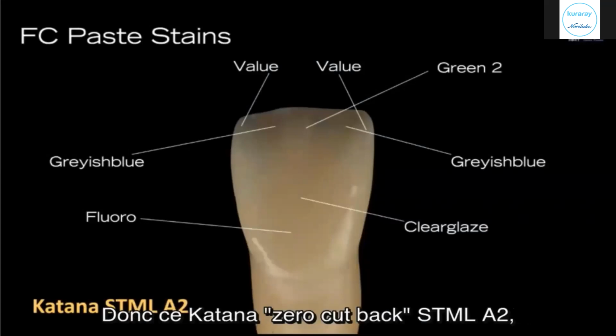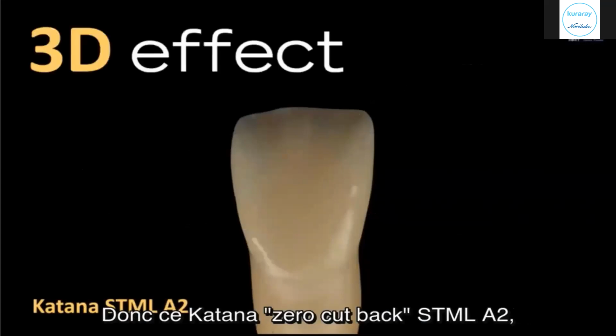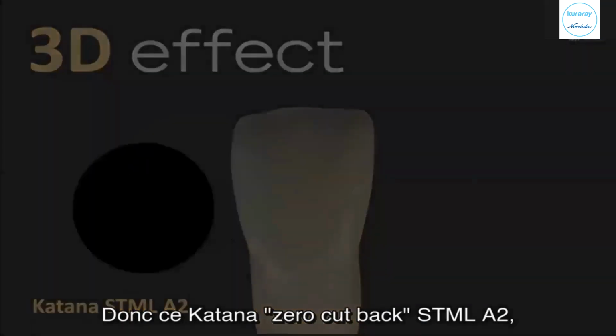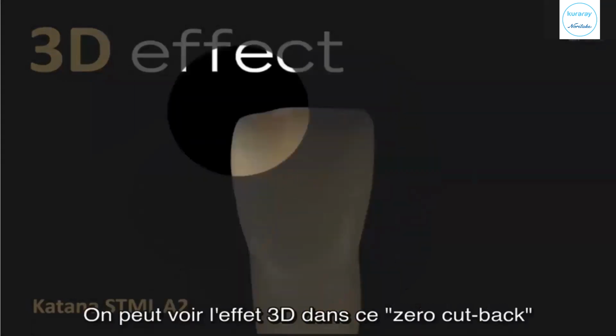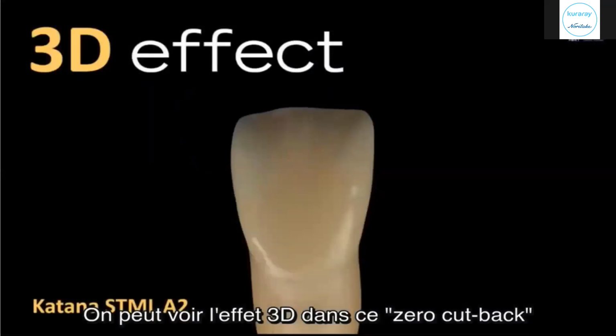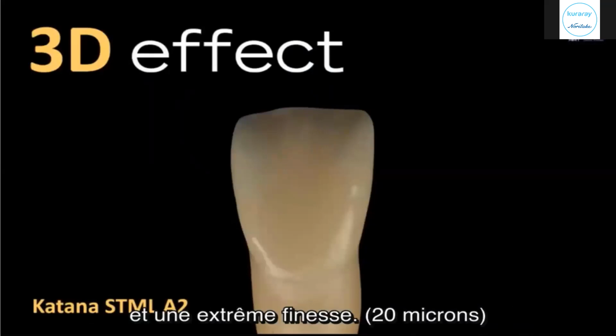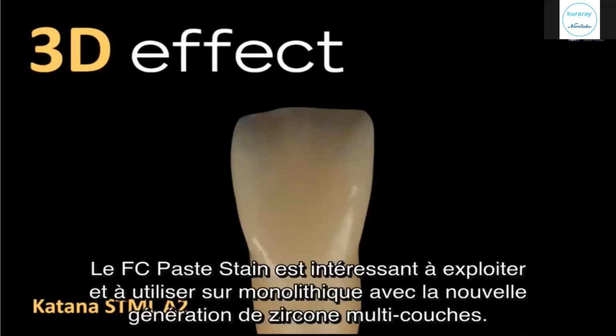So this is a zero cutback Katana STML A2, where we can see the 3D effect in a zero cutback, a 20 micron effect in thickness. No powder, no staining, no infiltration. It's really interesting, this kind of material, FC Paste, to use and exploit in the best way the full contour, using the new generation multi-layer zirconia.